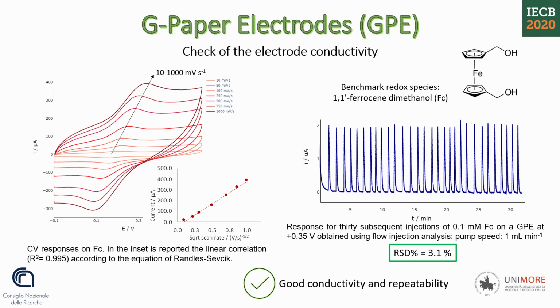G-paper electrodes were then tested using flow injection analysis. With this analysis, we demonstrate that the baseline is stable even if the measure lasts more than 30 minutes. And also tests by injecting ferrocene dimethanol show that the repeatability of the same solution concentration is very high, the relative standard deviation is very low.